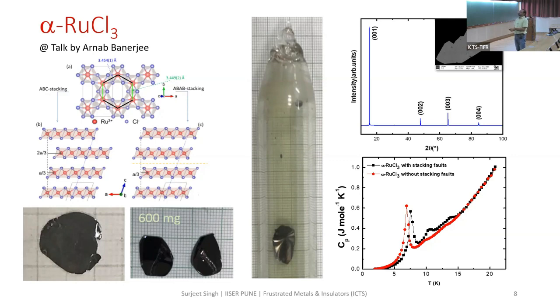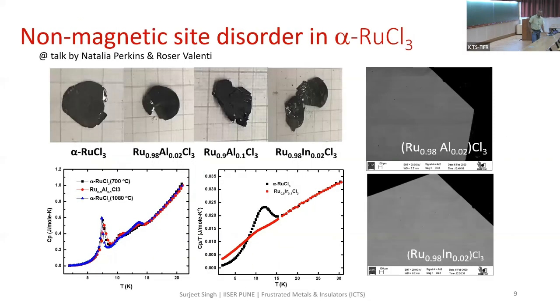I just want to tell you that we are also into growing RuCl3 crystals, and we have managed to get a large crystal of about 600 milligram with a fairly sharp specific heat anomaly, and which has a very little trace of the stacking faults, if any, because if there are stacking faults, you get these multiple phase transitions, which are indicated here with the black curve. So the idea was not really to grow RuCl3, but actually to go a step further, to dope it and to investigate the effect of non-magnetic doping.